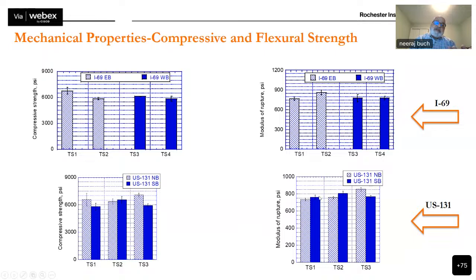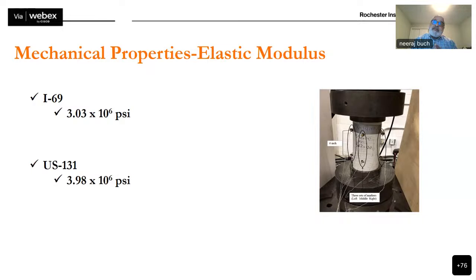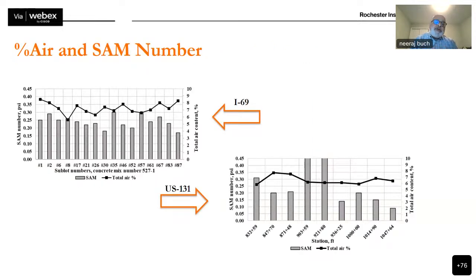The same goes with the modulus of rupture or the flexural strength. They were all in excess of 700 PSI or 750 PSI. So there really was no issue with meeting the target of compressive strengths or flexural strengths for concretes in either of the pavements. So that wasn't an issue at all. The same thing with the elastic modulus. Again, the elastic modulus was well within the acceptable range for the design and construction of concrete pavements. So again, there was nothing alarming about the elastic modulus properties of the concrete.